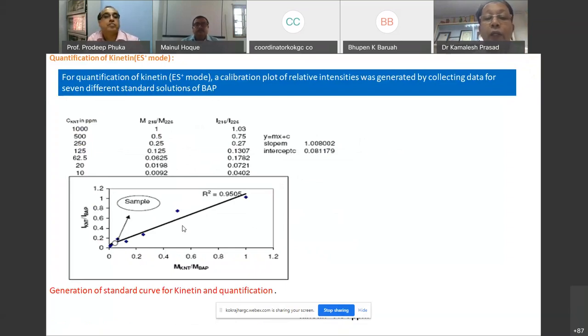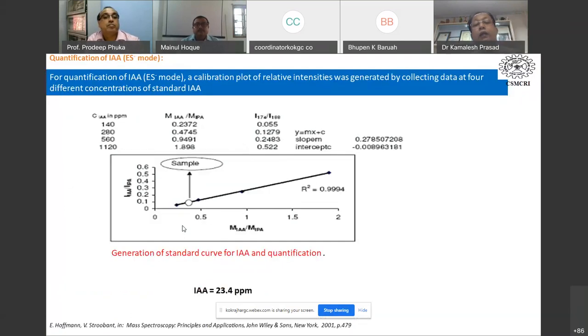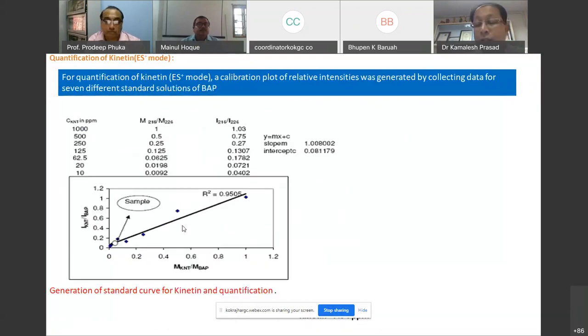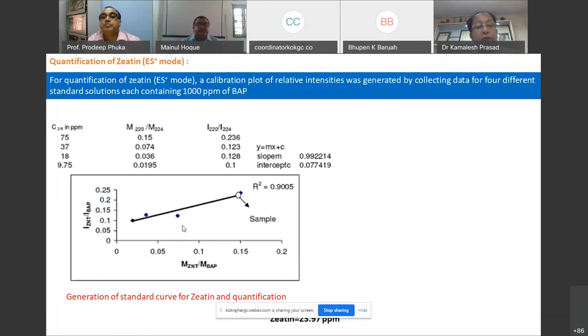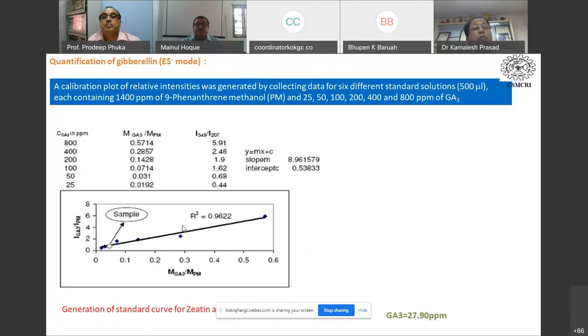So with this quantification, we have tried to do it for G18, then we tried kinetin, and almost with accuracy, we were able to quantify these. And these values were almost lesser than what we have detected by UV and HPLC, because here we are able to detect the particular molecule, not a common class of molecules. So this is what the G18 was quantified, coming around 25.97 ppm, and gibberellin was also quantified by this method, and it was coming around 27.90 ppm.